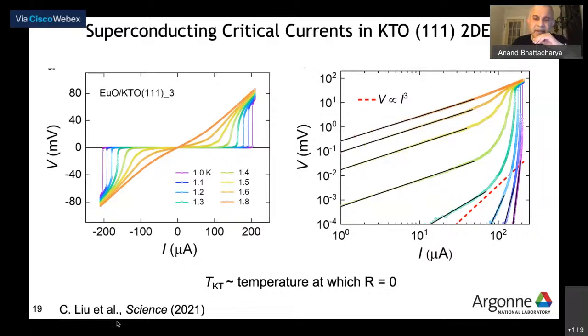by, again, the standard Kosterlitz-Thouless type thing, where the IV characteristic becomes steeper and steeper as you cool down. And then you pick some, we don't have data for V equals I cubed, but there is some region in this particular sample where that relation is obeyed. And actually we have measured in other samples, and that temperature is very, very close to where we can't measure the resistance hardly at all anymore. So it is consistent with the KT transition.